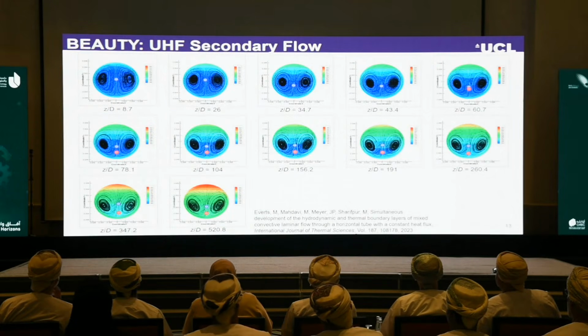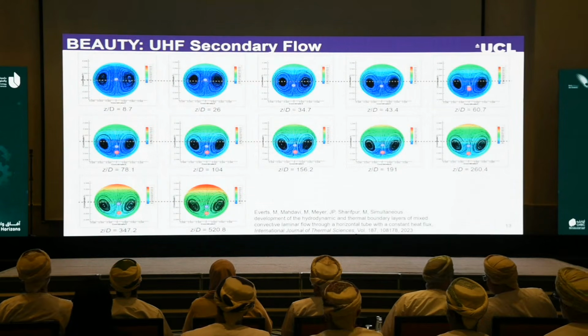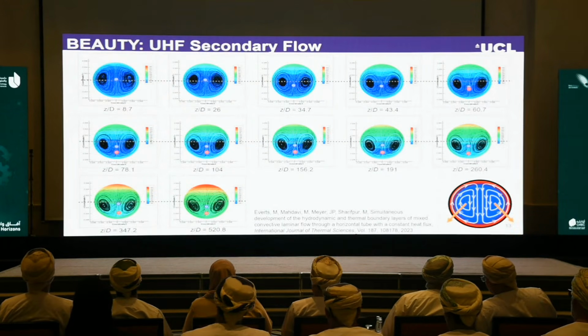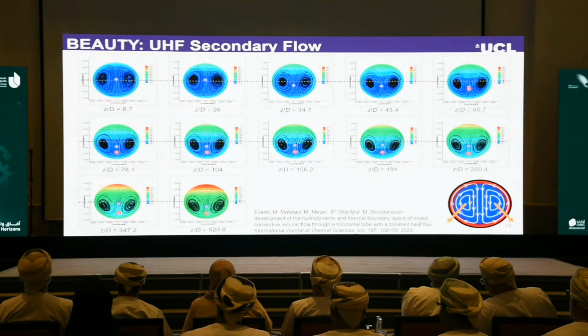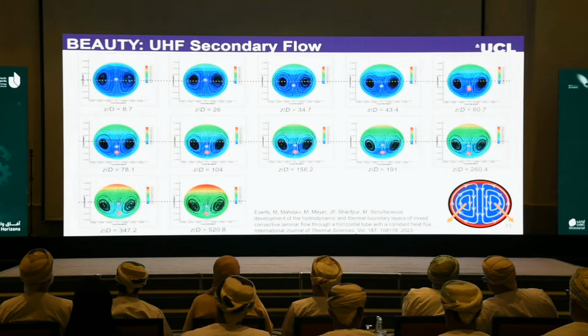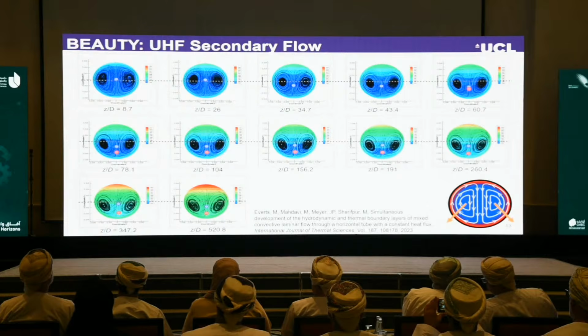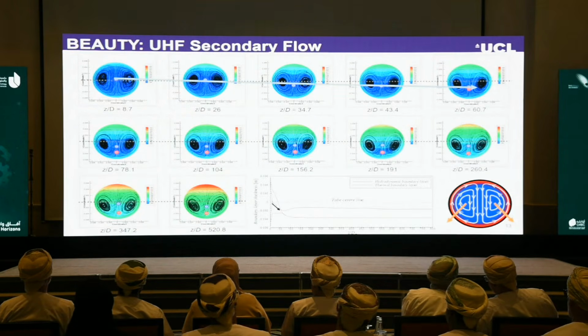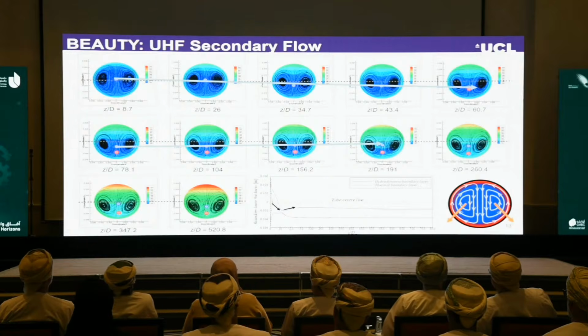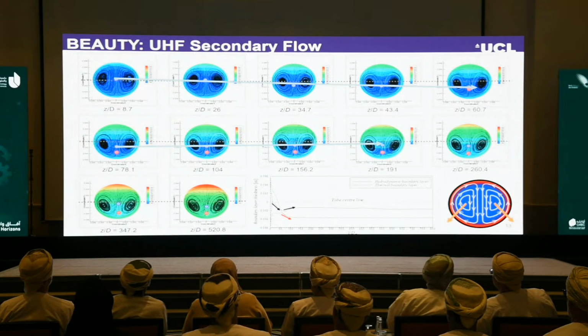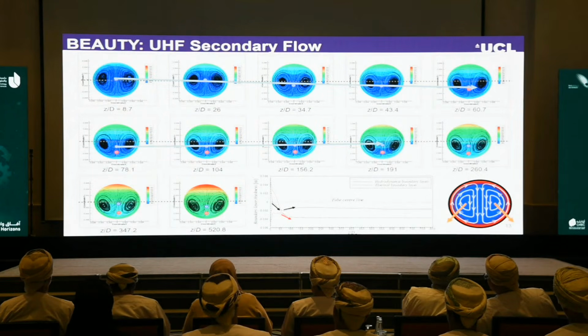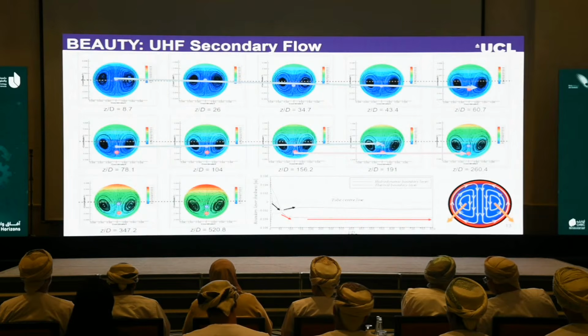inside the tubes. And as we can see here, the dotted lines, just for reference, represent the center line of the tube. We can see that the vortices, which is basically our secondary fluid motion, as it developed and became stronger, it moved downwards and towards the sides of the tube, which also explains to us why those merging points developed below the center line of our heat exchangers. So as we can see here, it starts very nicely in the center of the tube, then it moves downwards, and then slightly upwards before becoming approximately constant. And likewise, with the thermal boundary layer, this merging point, which is indicated by the red dots, first moves downwards and then it becomes approximately constant.